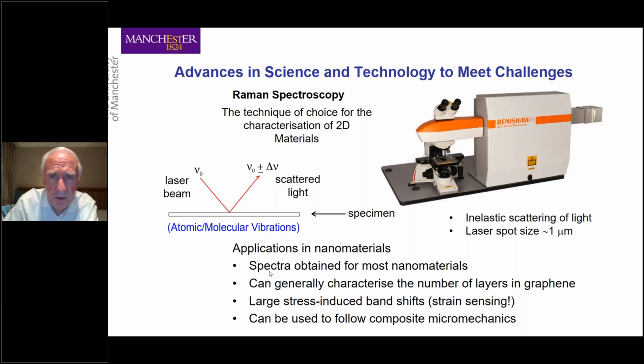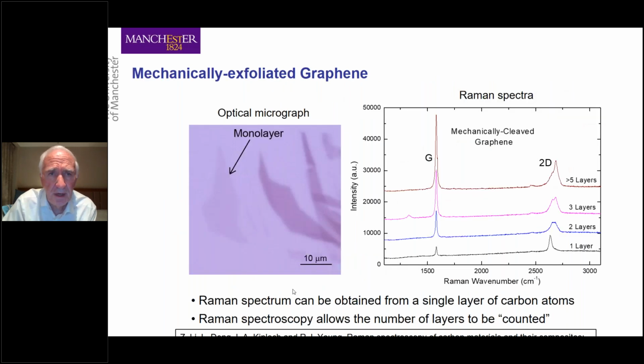And you can characterize many aspects of the material, particularly you can use it for strain sensing. We have a very recent review on this in Progress in Materials Science. Now, here's just an example of exfoliated graphene, just the flakes of exfoliated graphene: monolayer, bilayer, trilayer. And first of all, you can see that you have quite different Raman spectra for monolayer, bilayer, and trilayer.